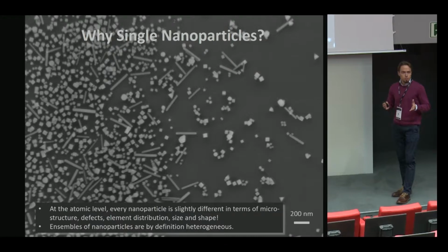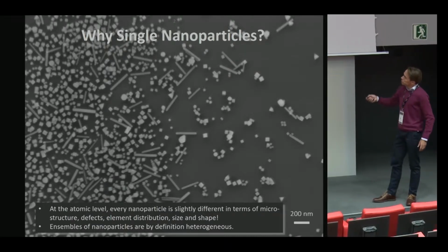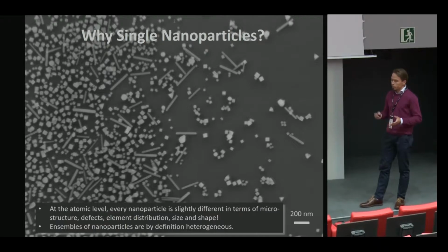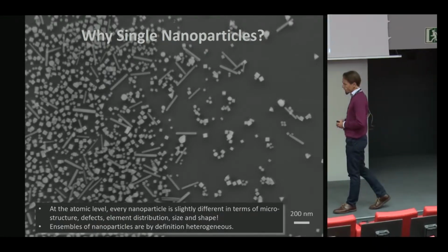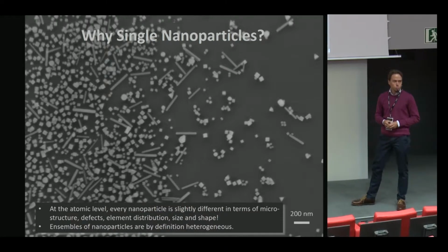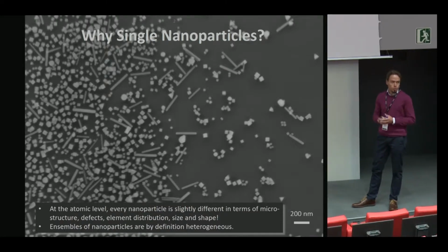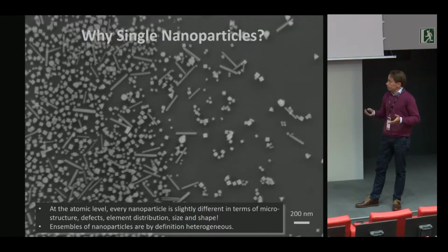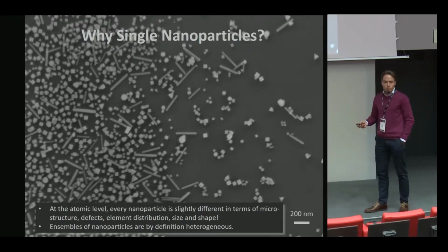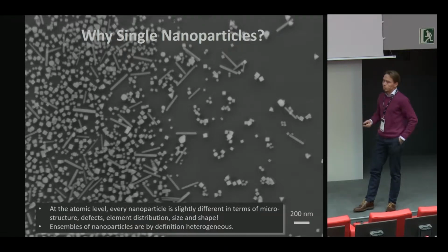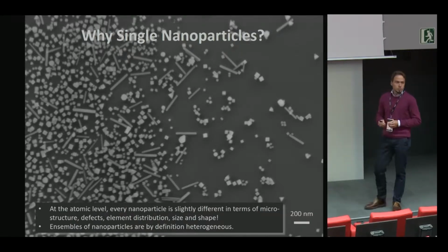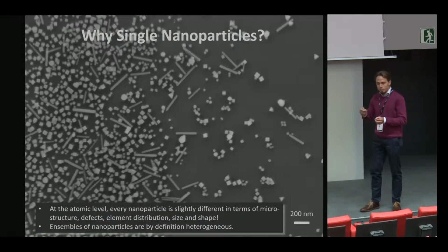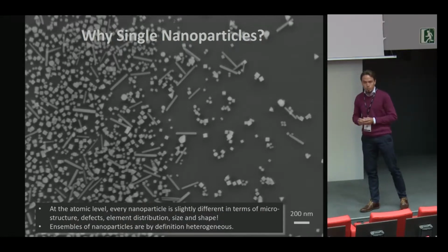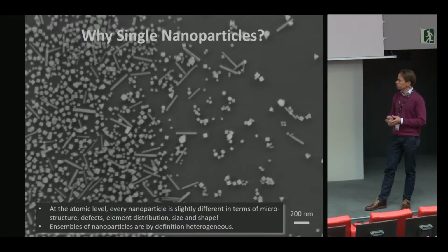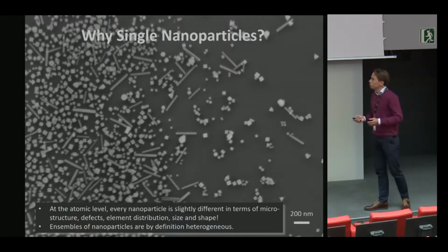So, why single? I think this SEM picture of colloidally synthesized palladium nanoparticles, which were supposed to be single crystalline cubes, pretty much shows it quite drastically. Because the fact is that nanoparticles, already at this level, you see the scale bar, but at the atomic level, there is no particle that is exactly the same as another one. So ensembles of nanoparticles will always, by definition, be heterogeneous. Now, why should we worry about that?